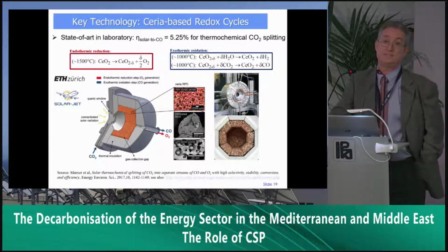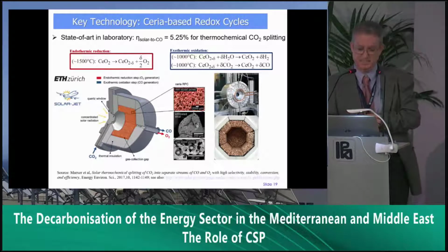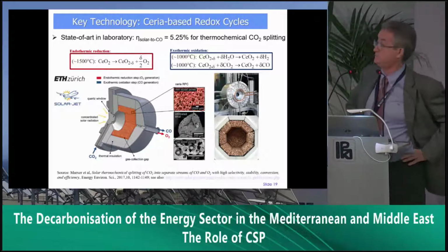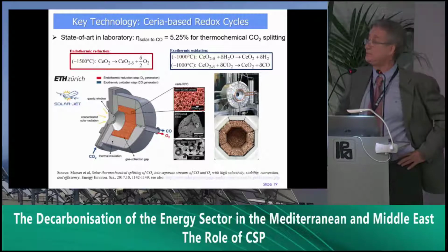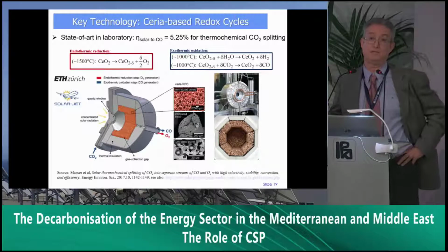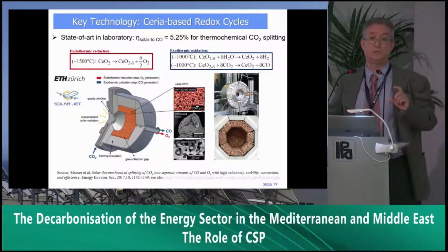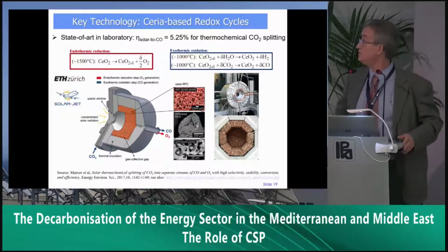What is, at the present time, in my opinion, the benchmark, the state of the art, is the experience reported by ETH Zurich in the Solar Jet project, funded by the European Commission, testing this kind of foam material with ceria. Ceria is a nice material because the chemistry is simple, only 2 oxidation states, and the material has very nice oxygen diffusion.